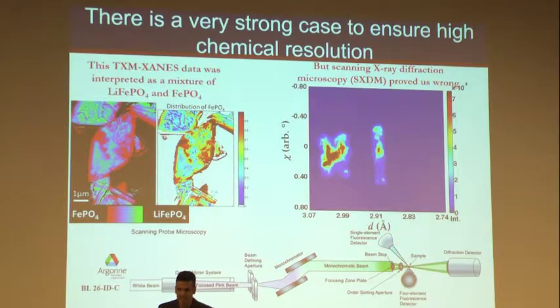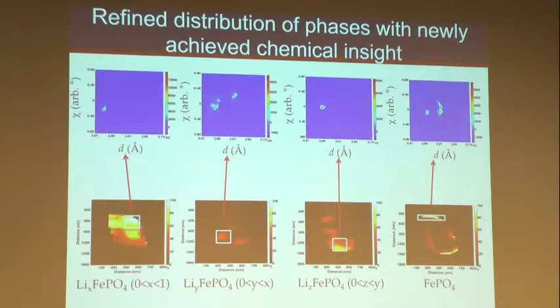And this creates a whole set of questions about what we knew about this system, perhaps the most studied system in the battery business. But I won't get to those details. I'll just proceed to show you what we did with the microscope. We not only used it to say, oh, there's 3 phases, or there's 2 phases plus a miscibility domain. We then located those phases in the particle. And that's what you can do when, instead of looking at the overall pattern, you look at each individual pattern for each position.